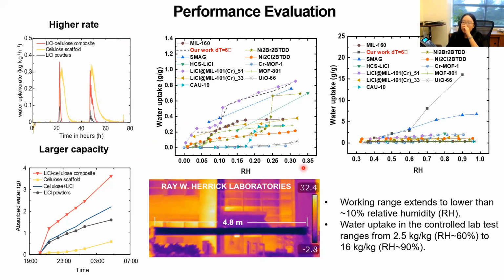This is a comparison with the current technology, like current materials for ambient water harvesting. It seems that after incorporating the salt here, we were able to extend the working range to as low as around 10% of relative humidity. And we're indeed looking at a pretty good performance. Our curve is actually the black one here, and here is the dashed line right here.